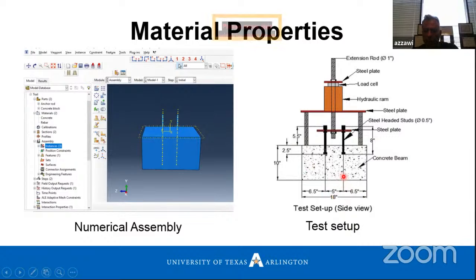So this is the test setup. We have these 2 anchor bolts, and we provide some frame here, and we test both anchor bolts at the same time. So we apply tension here. This is a load cell. We apply tension, and we test both anchors at the same time, not one anchor at a time. And we will see how much the grouping effect is on the strength of the individual anchor bolt. By the way, we have the strength of the anchor bolt individually. We already tested before, so we know how much this anchor can carry, as we see here from this table. These results are the strength of the anchor bolt individually without any grouping action.